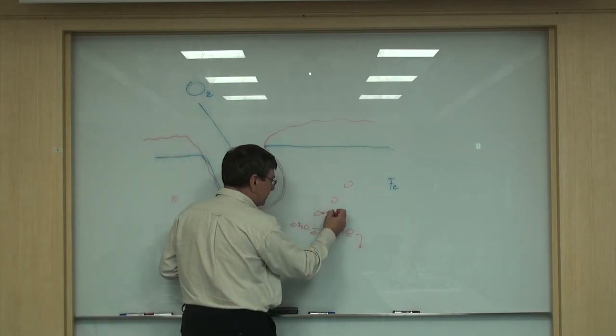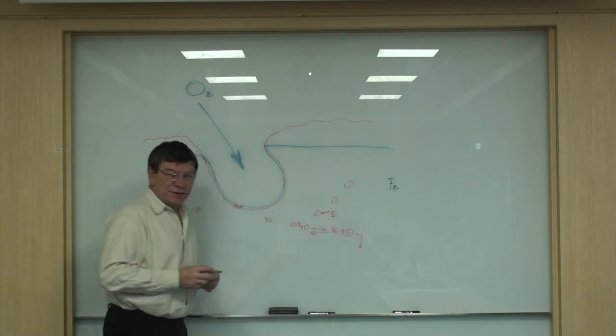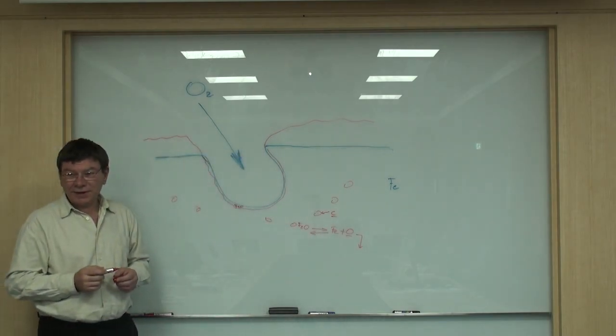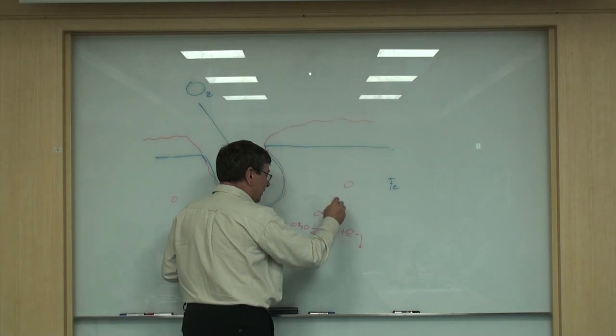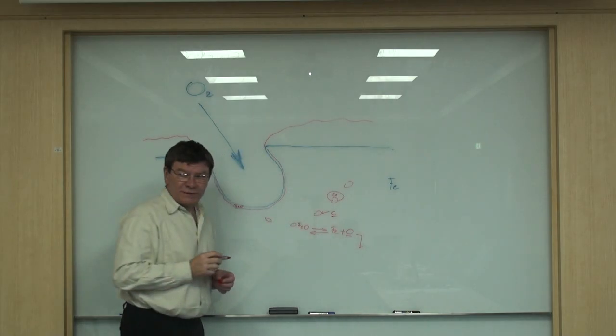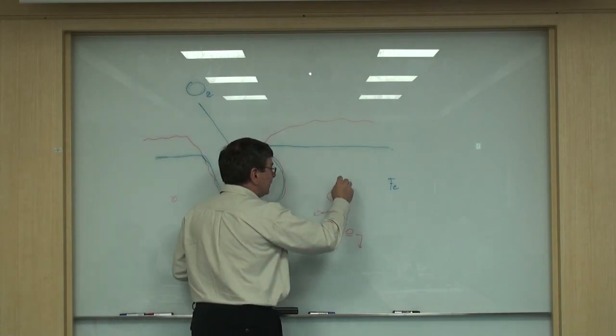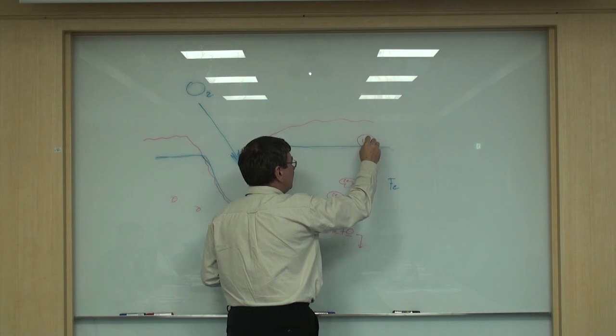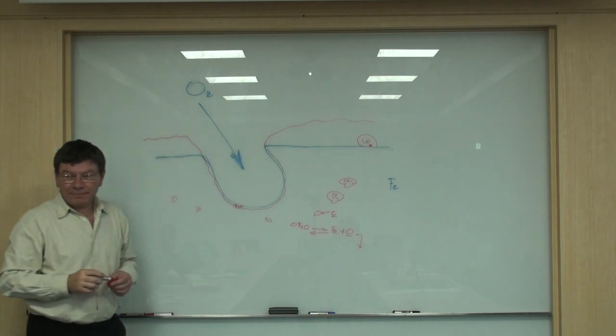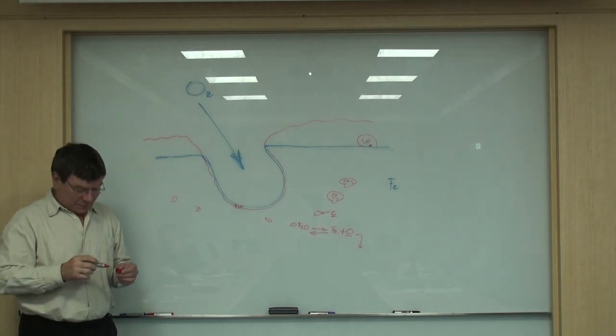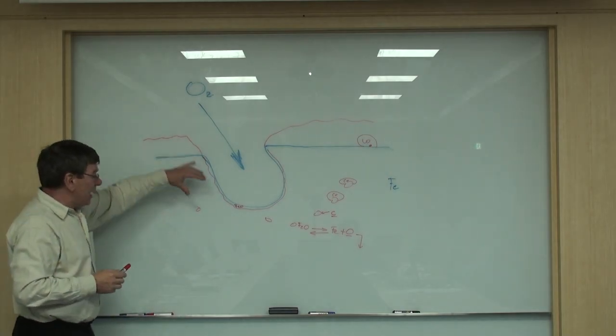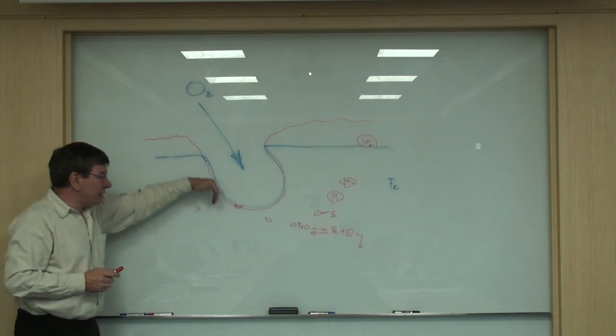And then the FeO is meeting sometimes carbon which is dissolved in the steel. Yeah? And you start decarburization and you create CO, small bubbles of CO. And at the end you have a bubble of CO and a remaining FeO. Okay? So this is what is happening at the impact of the oxygen stream.